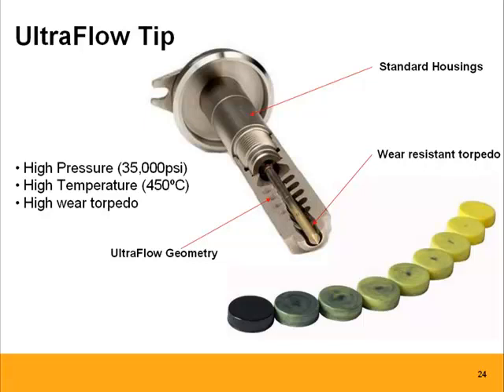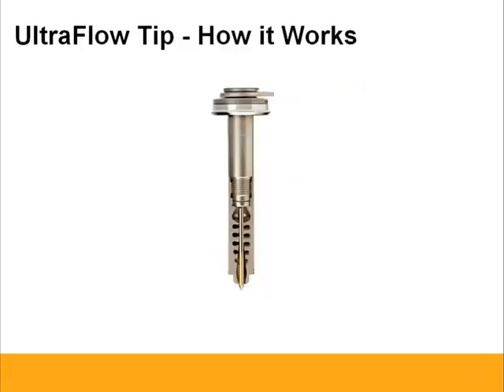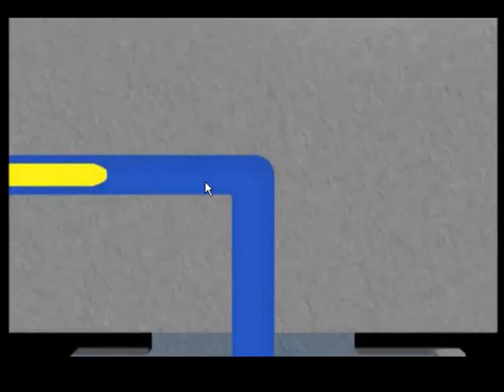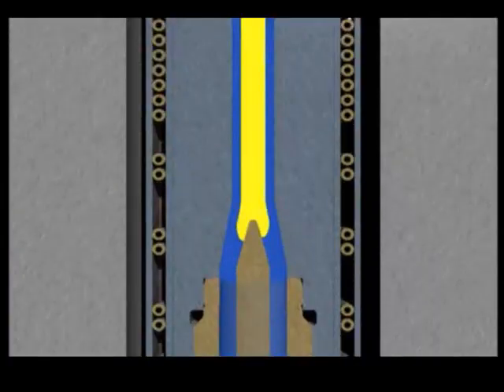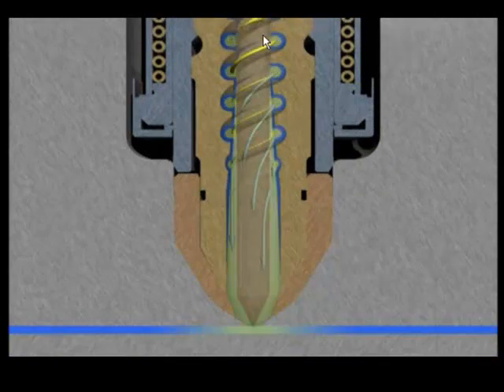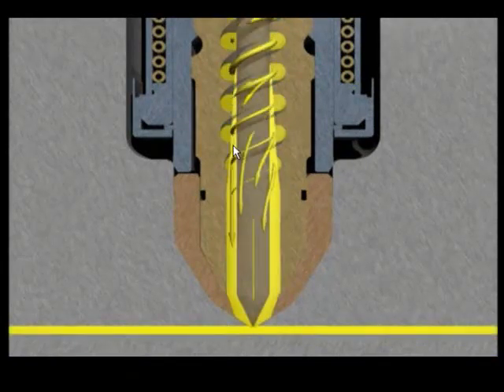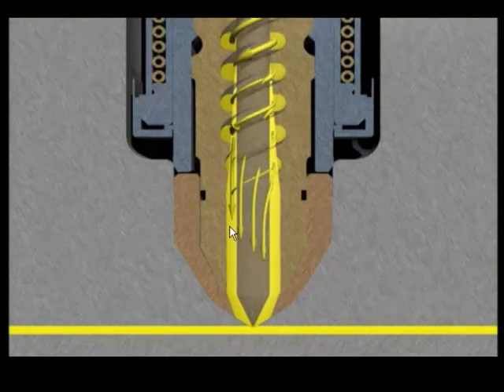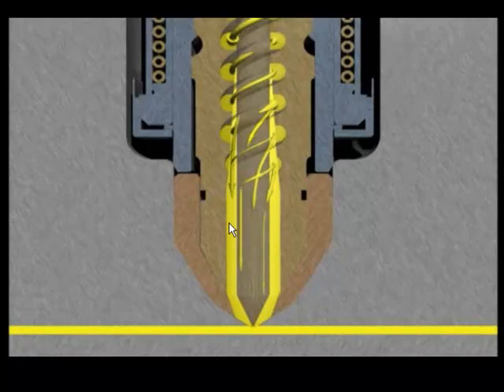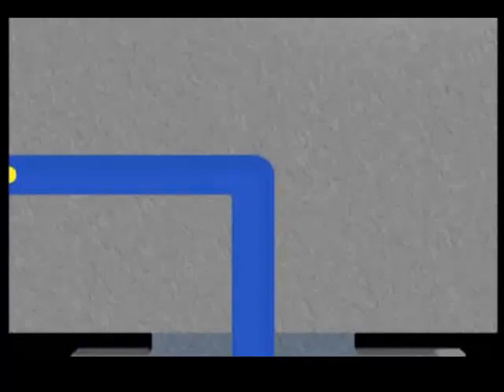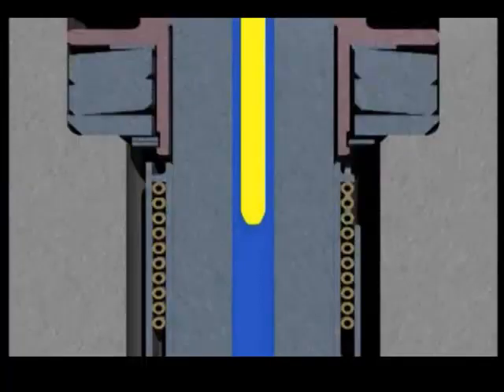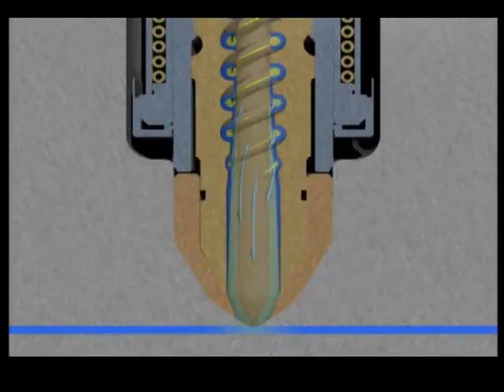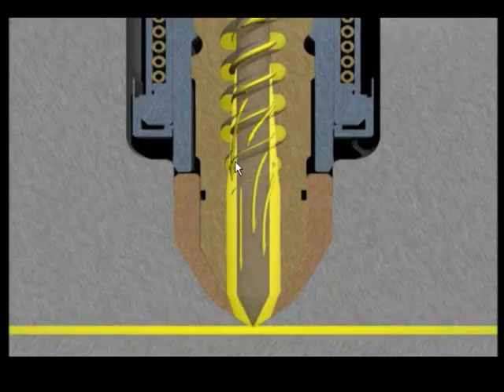I'll show you another quick animation that demonstrates how this works. I just want to remind you, this is right before the melt enters into the cavity. So we're demonstrating color change here, where the yellow color is trying to push the blue out. We're forcing the material first into a spiral, but at the same time, and very important, we're opening a gap and we get flow along the torpedo too. That's very important because we have to have both. If you only had the spiral, that wouldn't be enough because we cannot create turbulent flow with plastics. But if we create crossing melt streams, with one flow going this way and the other going along the torpedo, we actually create mixing within a hot runner system, or in this case within a nozzle tip.